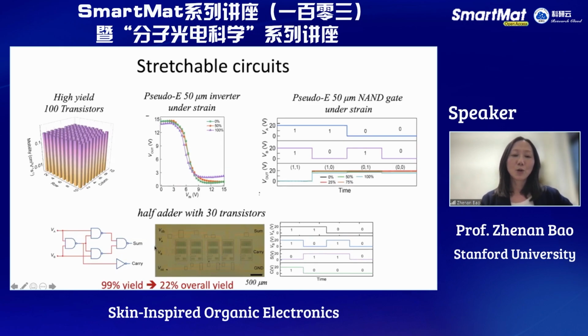And I mentioned yield is really important. For example, if we make a simple circuit that has this half adder, this circuit has only 30 transistors, but think about 30 transistors all working, each has 5 layers to fabricate. And if the yield for each layer is 99%, then if we want all the 30 transistors to work, the overall yield after fabrication would become only 22%. So that means essentially we need 100% yield for all the layers and all the transistors we make in order to really make a working circuit.